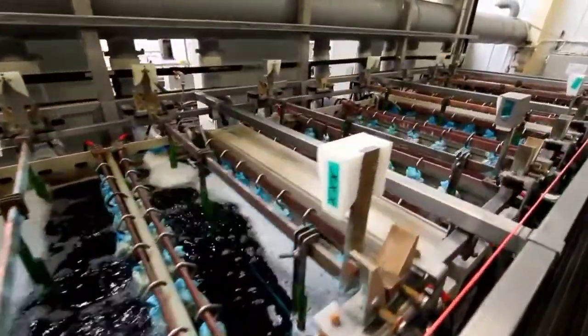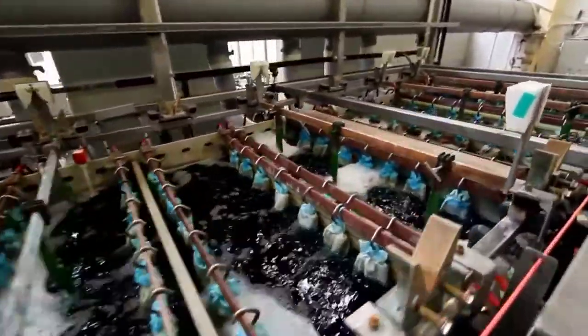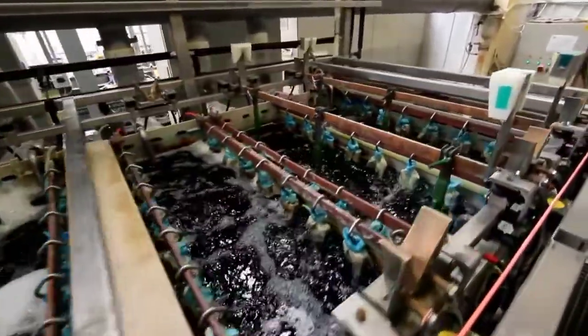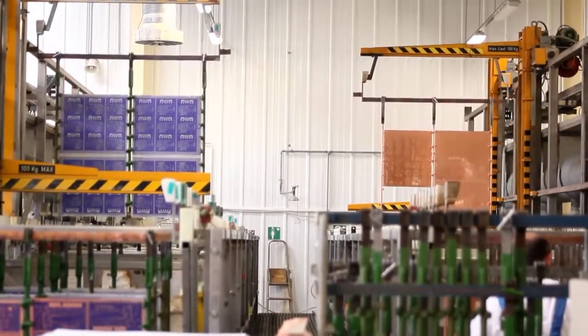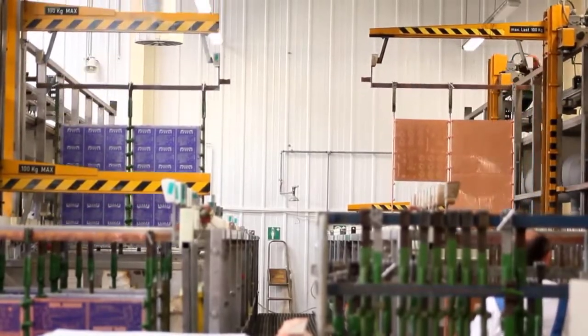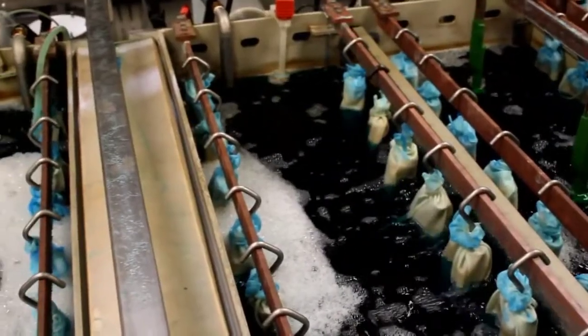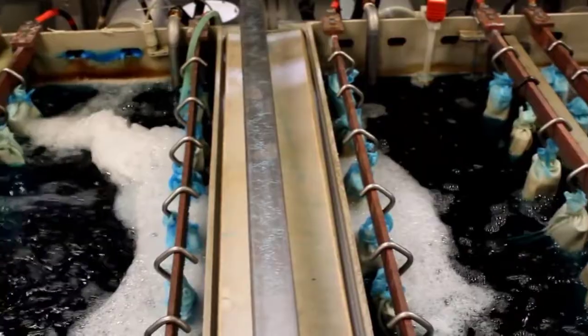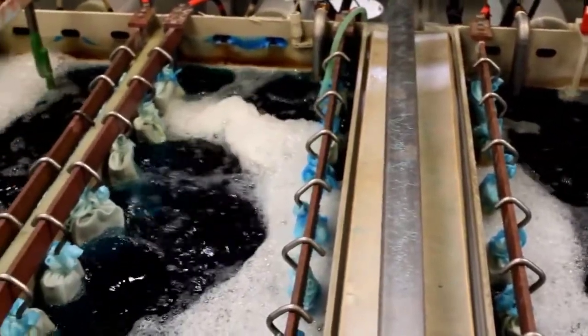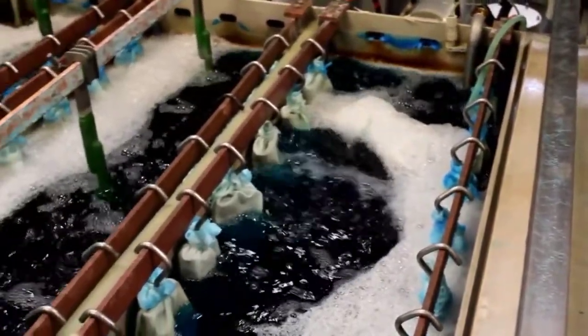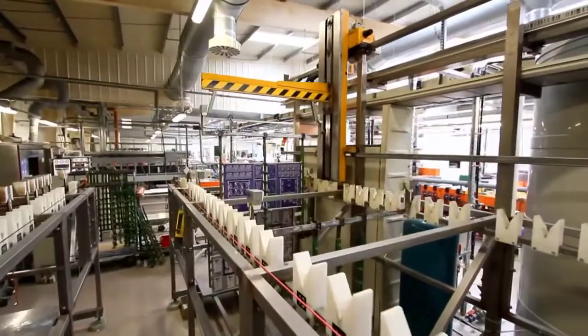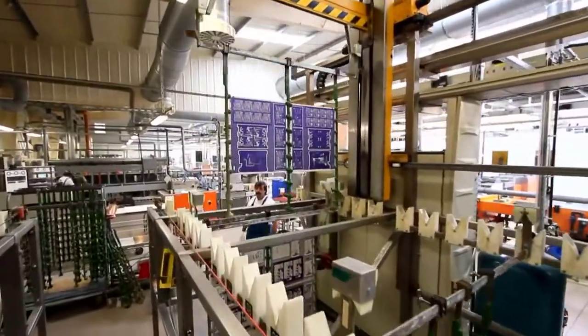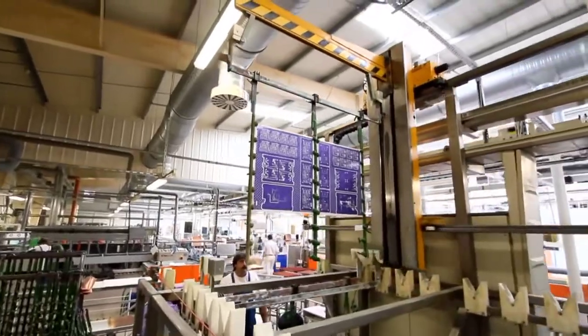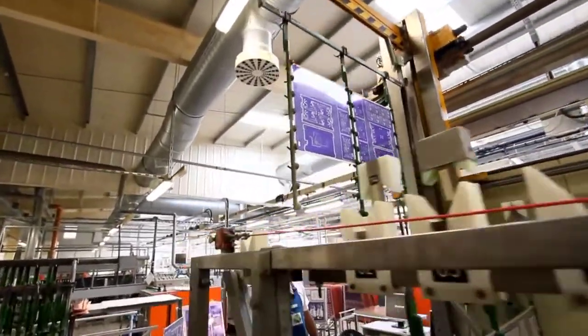To ensure good conductivity through the holes, we need to plate on average 25 microns of copper on the whole walls. This means that we also plate 25 to 30 microns on the surface tracks. So if we start with a typical 17.5 micron copper foil, it will be 40 to 42 microns after processing. The baths are designed to produce an even copper thickness across the panel. Modern chemical solutions also have good throwing power to produce an even thickness of copper right through the hole.